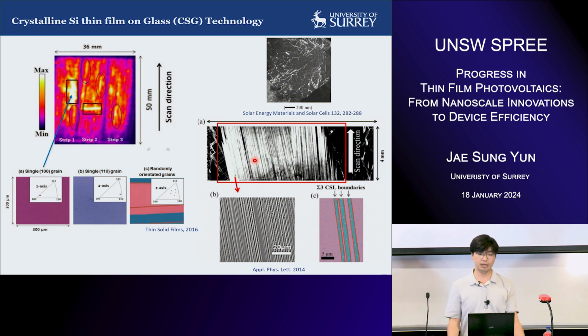But I did learn quite a lot during my PhD, where I could study the microstructural effect. For instance, this is the silicon thin film on glass, and we fabricated crystalline silicon film using a laser crystallization process. So we scan the laser to crystallize and fabricate high quality silicon thin film, and there were definitely some structural effects, such as the crystal orientations you can see. This PL spot here has a very high PL intensity, and you can see that it has a 100 grain. So I took this sample to EBSD and checked why this spot has very high PL intensity, and